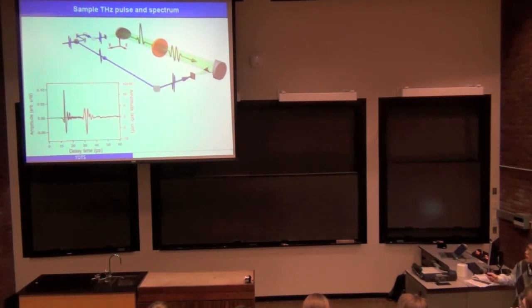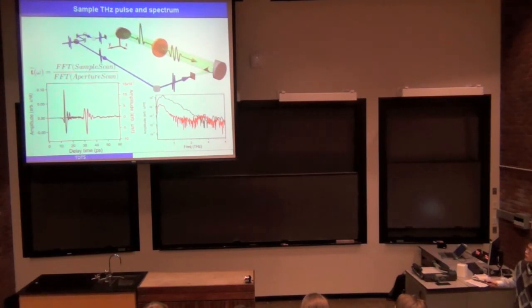And when we put in a sample, because the sample is usually optically thick, the pulse needs to travel more distance. As a result, the terahertz pulse would be detected at a later time. And if we take the FFT of the pulse, we get this red curve here. Usually, the FFTs of those two pulses are complex spectra, and here I just showed you the magnitude. The ratio of the FFTs of those two pulses will give us a complex transmission function, from which we can obtain the complex conductivity or other related material parameters.